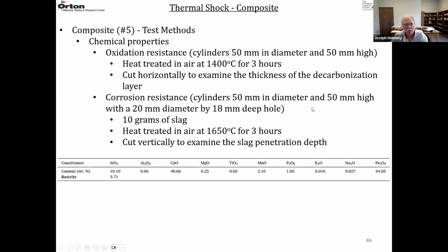They took these cylinders, drilled a hole 20 millimeters in diameter, 18 millimeters deep, and filled that hole with 10 grams of slag, and they heat treated those cylinders with the slag in air at 1650 degrees C for 3 hours. And then they made a vertical cut and examined the slag penetration depth.